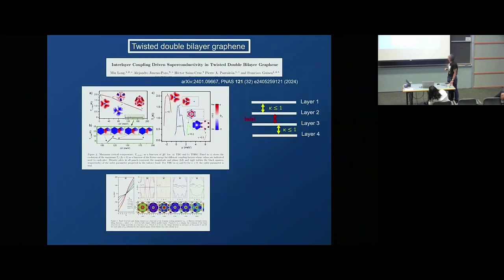And the last thing we did was to look at a twisted double bilayer, which is a system very similar to a twisted bilayer. In order to be sure what we were doing made sense, we interpolated, and what we did was, we are theorists after all, we had a twisted bilayer with 2 layers, one above the other below, and we tuned the coupling within each bilayer. So we could interpolate between a twisted bilayer and a twisted double bilayer.